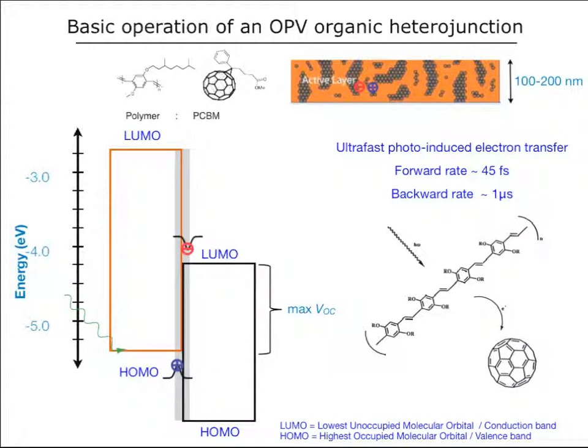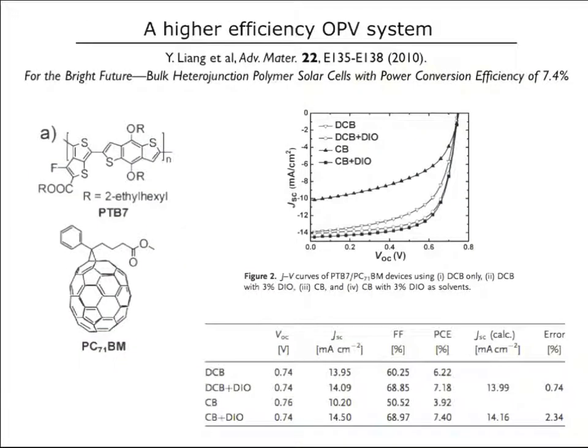So that exciton should, in principle, diffuse to the interface where there's an intermediate step called a charge transfer exciton. At least we think that exists. This will exist for a few femtoseconds. And then finally, there will be real charge separation where there's an electron on the accepting material and a hole on the donating material. So importantly, this forward electron transfer process is an ultra-fast one. It's been measured by Christoph Brabec at something about 50 femtoseconds. But the backwards rate, the recombination rate, is extremely slow, something like 1 microsecond. So it's this asymmetry between the two rates that really enables the organic solar cell.